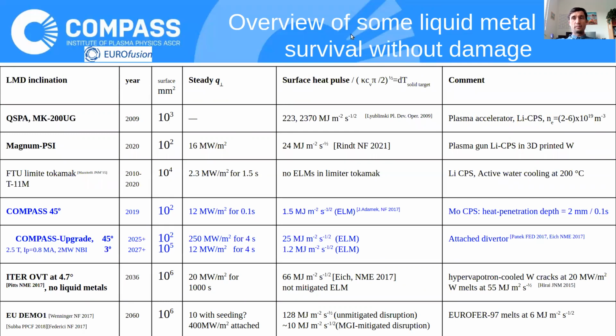Here is an overview of some liquid metal plasma facing components where they've survived without any damage. We start in 2009 with QSPA and the MK200 device in Russia, where a surface of 1000 millimeters squared was exposed to a heat pulse of 2370 megajoule per square meter and square root of a second by Igor Lublinsky. It was a plasma accelerator, with plasma pretty similar to what we have in today's tokamaks. And you can see that the heat pulse is even stronger by an order of magnitude than what is predicted in future ITER or even a DEMO reactor in unmitigated disruptions. So for heat pulses, it's an interesting plasma facing component.